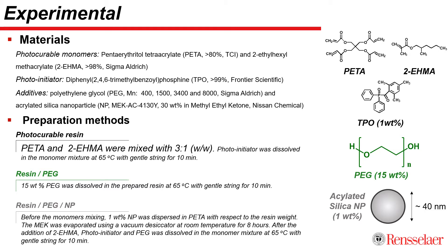For the photopolymerization phase separation study, we used polyethylene glycol with various different molecular weights and acrylated silica nanoparticles as the additives. Polyethylene glycol was added at 15 weight percent and nanoparticles were added at 1 weight percent to the resin.